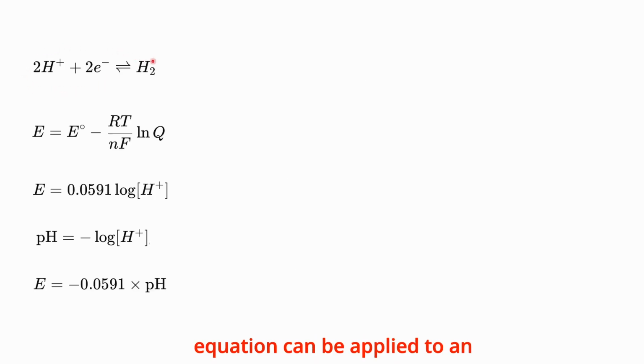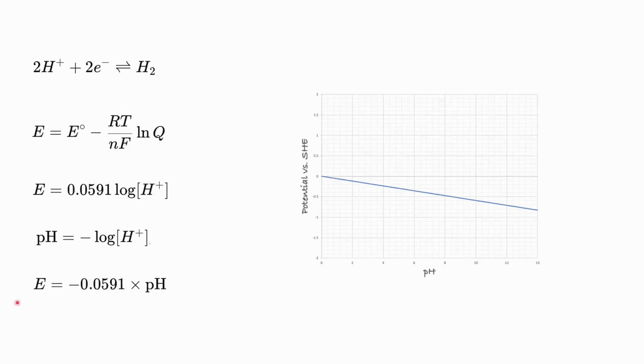This expression of the Nernst equation can be applied to an equilibrium involving hydrogen gas and hydrogen ions. If we do the maths, the equilibrium potential for this equilibrium at room temperature and under a hydrogen pressure of 1 atmosphere is minus 0.0591 times the pH value. Having derived this equation, it can be plotted on a potential versus pH graph. This equation generates the line corresponding to this specific electrochemical equilibrium. For conditions above this line, the oxidation reaction is favored. Conversely, for conditions below this line, the reduction reaction is favored.